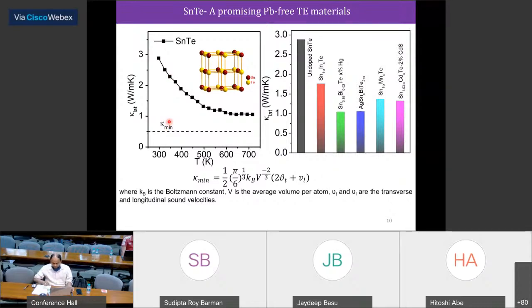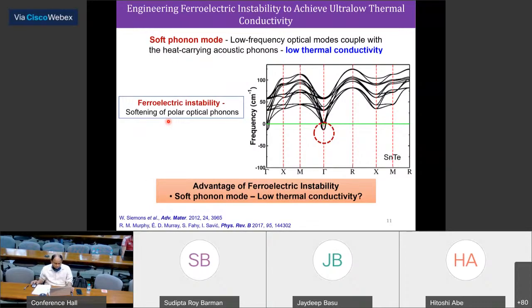So in order to do that, we know we can decrease the thermal conductivity if we can create soft phonon modes, which can actually scatter the heat carrying acoustic phonon mode and can give rise to low thermal conductivity. And then we came across the phonon dispersion of this rock salt tin telluride at 0 Kelvin. You can see there is a ferroelectric instability coming due to this optical phonon modes, which is well known in the literature.